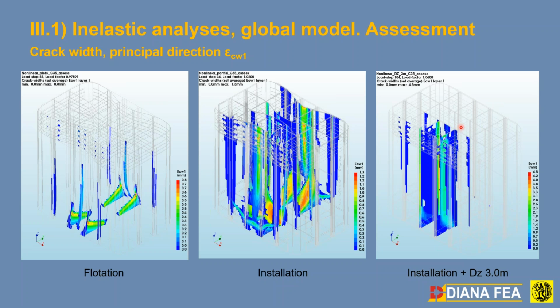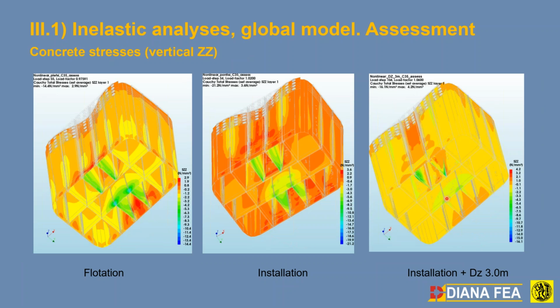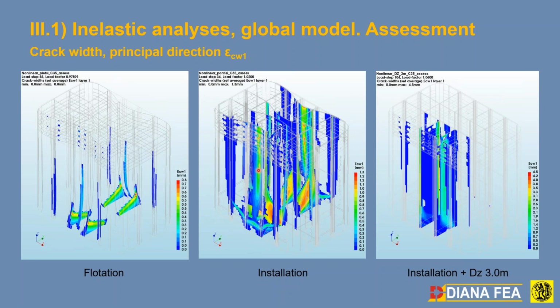So these walls here practically are under transverse bending because of the differential head, as well as in plane shear because of the out of plane hydrostatic forces, the unbalanced hydrostatic forces. This is the case, of course, as if nothing would have happened. There would be no breach of bulkhead, and the caisson was, this is pretty much more or less what happened in the previous caisson when this thing touched down and everything went back to normal.